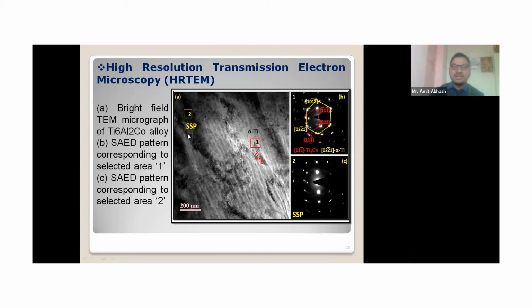So by going through this bright field HRTEM image and SAED pattern, we confirmed it. These are the HKL values, and using these HKL values and the XRD pattern, as we have gone through, this is the Ti2Co 111 plane, and this is the alpha titanium 022-1 plane, and the same I have got in the XRD values. So if you calculate it, definitely this will match with the XRD data also. This also confirms the formation of alpha titanium and Ti2Co lamellae. The more characterization you do, the more accurate your result, and the more you can predict your result.